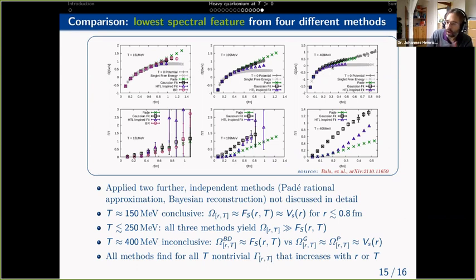And as we go to 400 MeV and so into the regime of LHC, what we now see is that some of the calculations are consistent with 0 temperature, while this HTL-inspired fit indeed looks very, very similar to the Debye-screened singlet free energy. And all of these results find finite values for the imaginary part that are quantitatively important and get bigger as we increase the temperature.